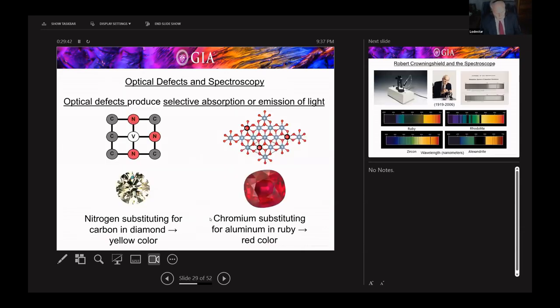So this is a couple of examples on the left. This is a two-dimensional representation of the carbon atom arrangement in diamonds. And when you have nitrogen symbolized by the N, and a vacancy, which is a missing carbon atom, when you have that type of defect, the diamond will take on a yellow color. Whereas if that defect were absent, it would be colorless. In a similar way, if you have chromium substituting for a few of the aluminum atoms, that causes ruby to have a red color. So it's these optical defects that produce selective absorption or emission of light.